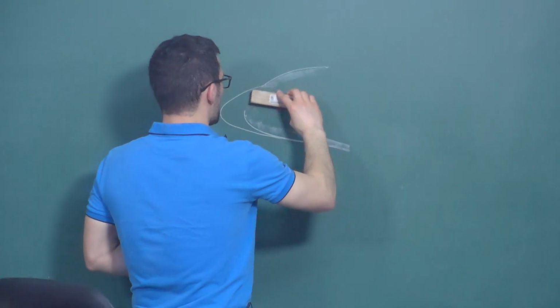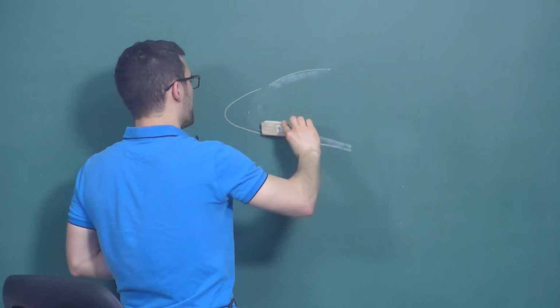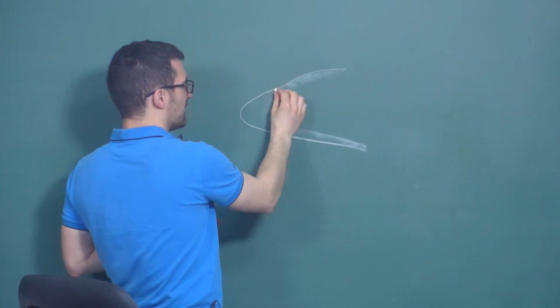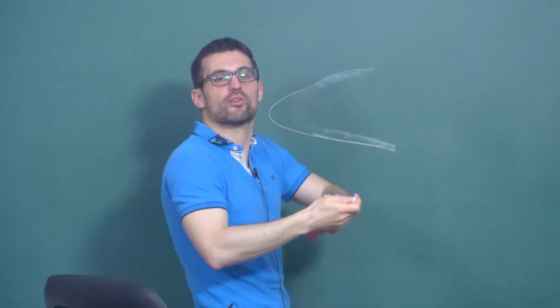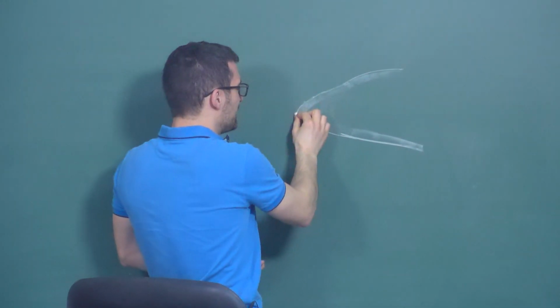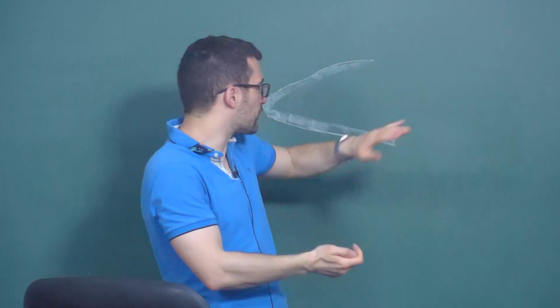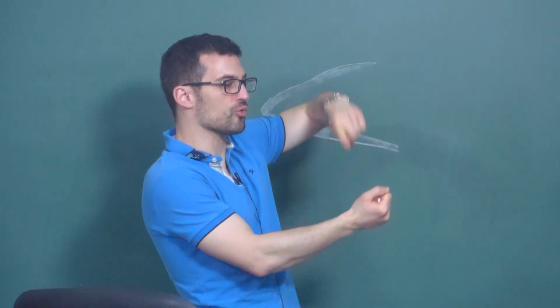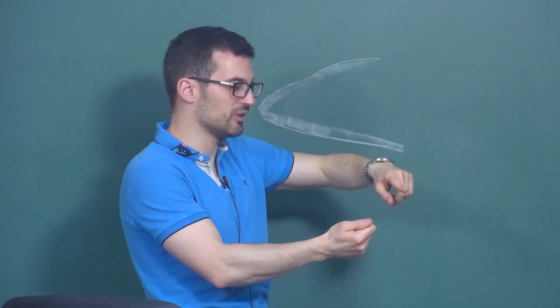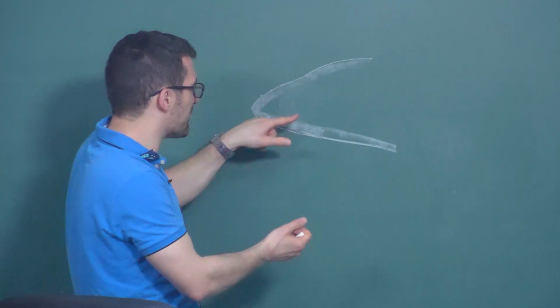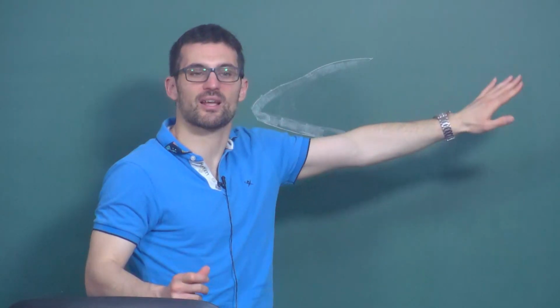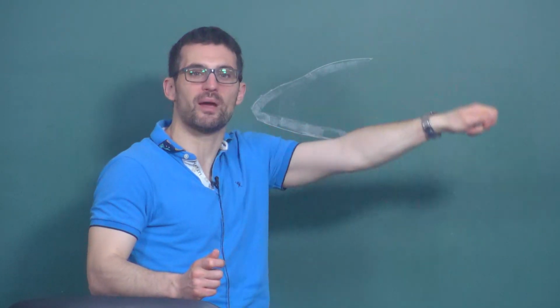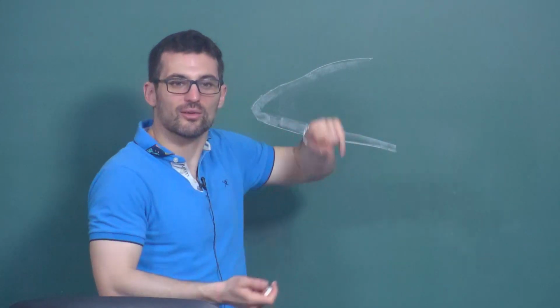This thing you rupture, get more corrosion, but again, you quickly start forming the film again. But now it's like you're applying a new paint. So this new paint has never seen any applied load yet. It's a completely new paint. So the cyclic process starts again. So you're doing an experiment where you're progressively increasing your load, you rupture a film, you progress your corrosion front. Now you are depositing a film again, but this film hasn't seen all the history before. It's like you applied a new paint. So the counting of the critical strain starts again.